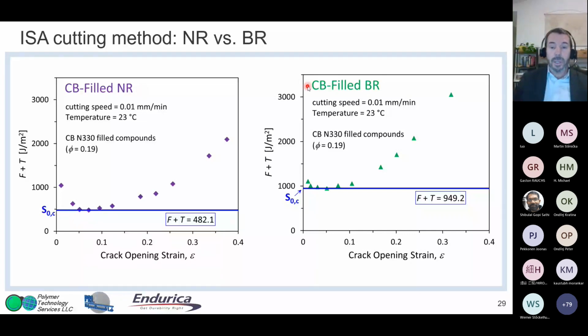Here's carbon black filled butadiene rubber. And without doing anything to the data yet, to actually pull out a T0, you can already see that pushing a blade into carbon black filled butadiene rubber almost requires double the force compared to natural rubber. Say, wow, I thought you just told me earlier that the tear strength of natural rubber is 6 times higher, nearly 6 times higher than butadiene rubber.